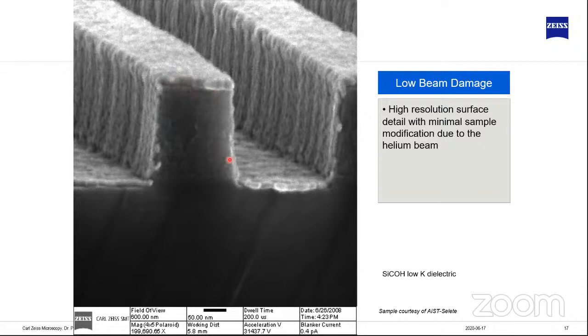If we're imaging that with helium ions, what happens is the beam just penetrates very deep into the sample. It does not do a lot of interaction with a sample surface. The other thing is we're imaging with very low currents. So in an electron microscope, you would typically use something like 100 picoamps. In the ion microscope, we use 0.1 picoamps to image. That means we're a factor of 1,000 lower in dose. And that means we do not generate any shrinkage of these structures, and that means we have the capability of imaging very delicate samples without modification. And that's quite interesting as it's an ion beam and not an electron beam.